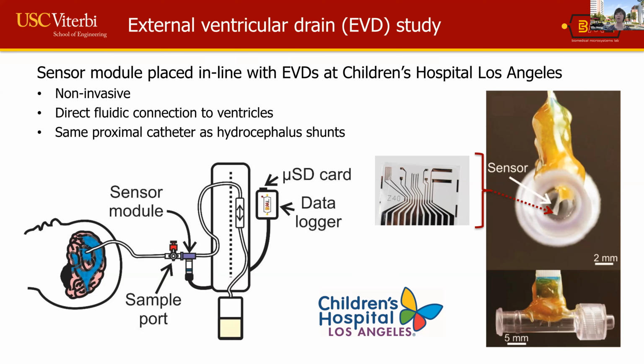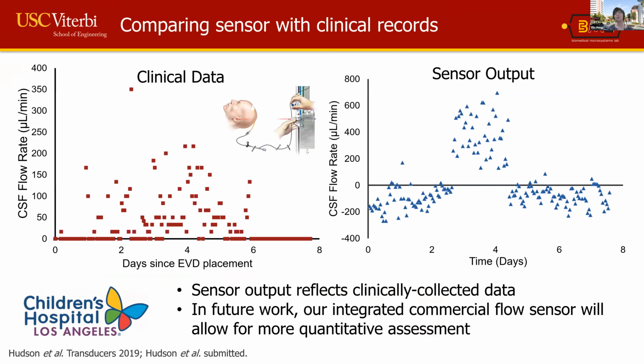And so these are all done. We have an IRB approved at the Children's Hospital Los Angeles, and we've done a couple of these. And so I'll show you very quickly, and then I'll wrap up so that there's some time for questions. This is some of our initial data taken with these devices. So I mentioned earlier that the clinical external ventricular drains are very simple devices. The way flow is monitored and recorded by nurses is that they actually take the collection bag, this item here in the center, and they weigh it periodically.